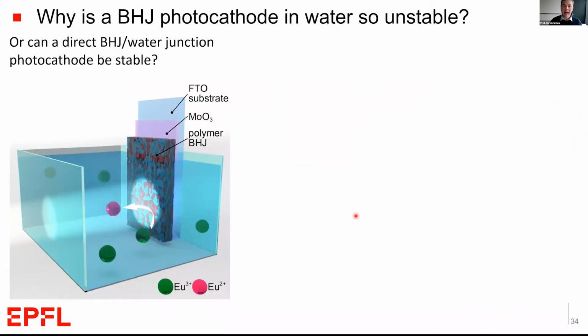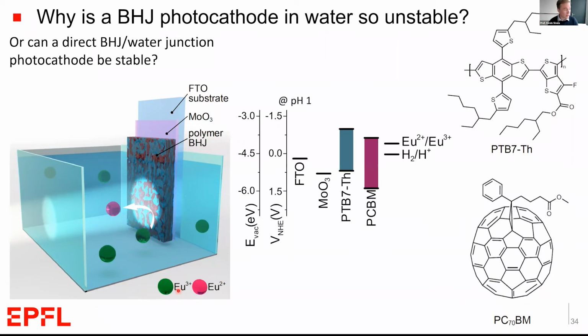So to do that, we took away the strict requirement of the photocathode to actually make hydrogen, and instead said, well, can we reduce something else that's a lot easier? For example, can we reduce europium-3 that's dissolved in water to europium-2? And we can imagine this type of system where we used a transparent electrode with a molybdenum oxide layer to help align the work function.